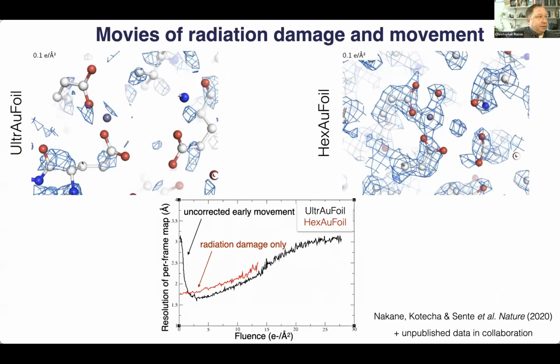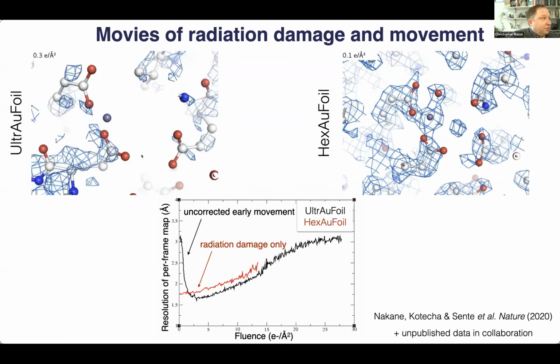Well, the idea is, let me just show you one more video here of data, and just to try and convince you that this really is real and important. So this is a very high resolution structure of apoferritin that was determined on an UltrAuFoil grid. So an all gold grid, our previous generation ones, but with a larger hole size. And this is one of these really high resolution, 1.2, 1.3 angstrom kind of deals. But you can see in the first 0.1 electrons per angstrom squared, the density actually doesn't look so good.